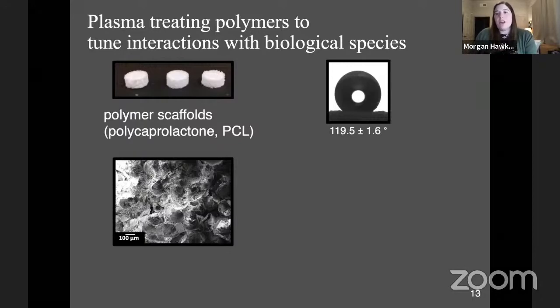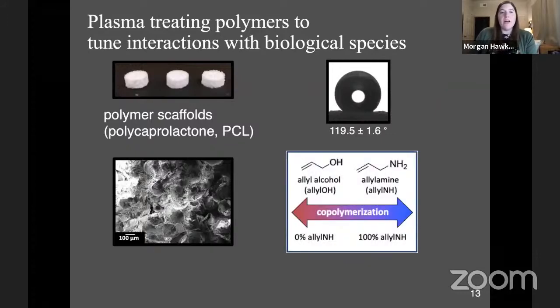So the goal of this project was to enhance the hydrophilicity of the PCL scaffold to enhance the cell attachment on the scaffold surface. So I took an approach where I actually used two different plasma precursors, one allyl alcohol and the other allyl amine. And I studied the effect of treating the scaffold with each precursor independently, as well as the precursors in different mixtures in the gas phase. So creating this mixed gas system, and that's referred to as plasma copolymerization.